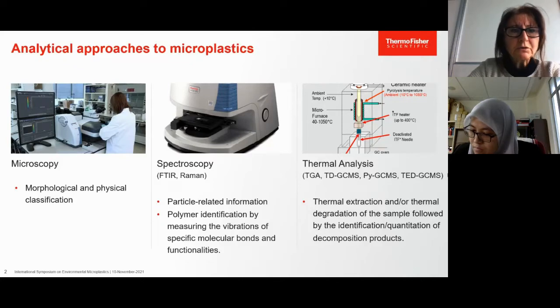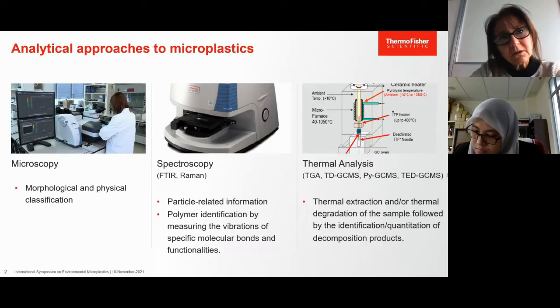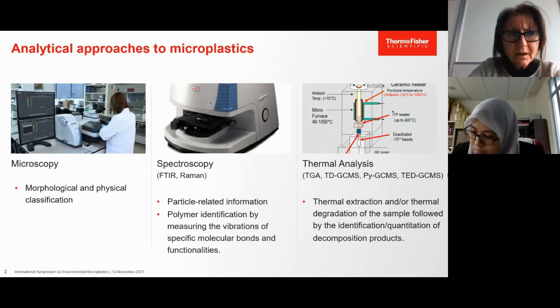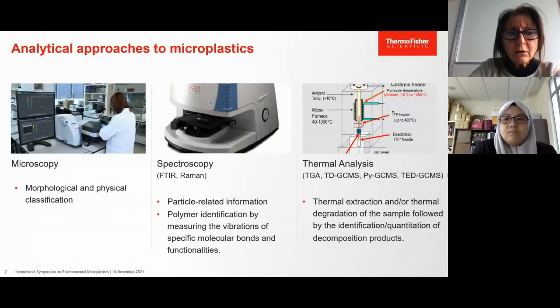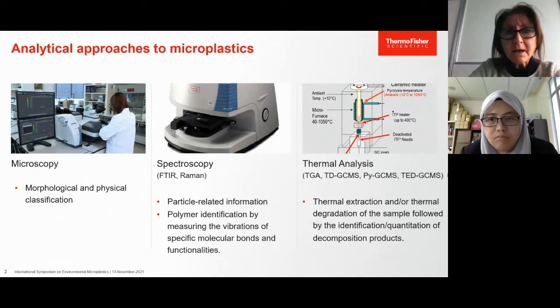However, in order to retrieve mass-related information, it is necessary to apply thermoanalytical methods where the sample is thermally heated or decomposed, and then it is analyzed for identification and quantitation of the extracted compounds or the decomposition products. Thermal analysis includes TGA, thermogravimetric analysis, thermal desorption, pyrolysis, thermo-extraction desorption, and all of those can be combined with the GC-MS for mass quantitative and qualitative information.